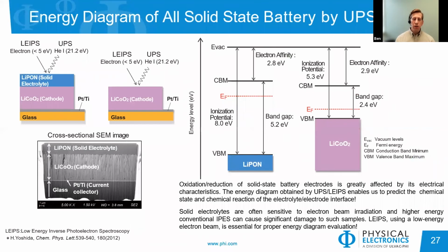Another technique we could use, this is an addition to the VersaProbe, is to do an electronic characterization using UPS and LEIPS. UPS is ultraviolet photoelectron spectroscopy. LEIPS is low energy inverse photoelectron spectroscopy. So just as the names imply, I'll show on the next slide. With UPS, we are irradiating the sample with a UV source, about 20 eV, and then we are detecting photoelectrons. So very much similar to XPS.